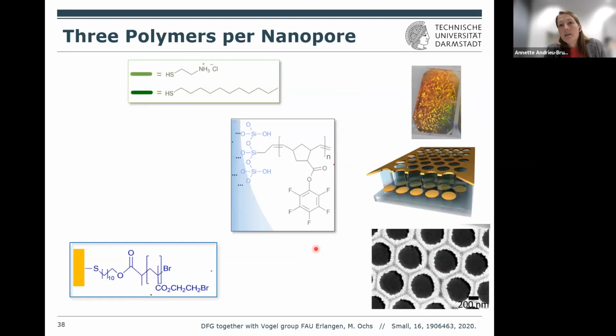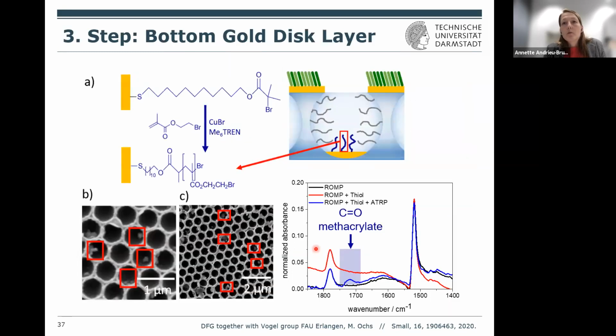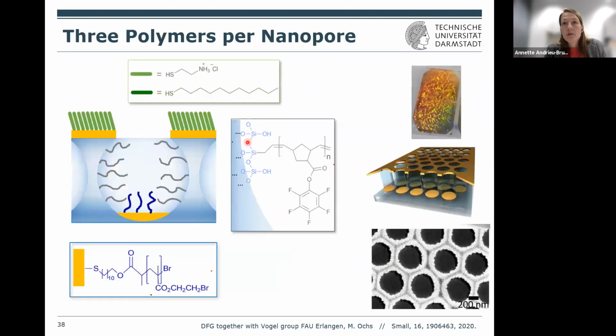And then, I didn't include the XPS data, which as well show all these functionalization steps, although it's quite difficult because this is quite deep inside the pores. So the analytics is not that easy, but the XPS spectra as well show the different elements of the different functionalization steps. So this was one approach, combining inverse opal monolayers with orthogonal surface chemistry and different wettability steps to get 3 different functions into each pore.